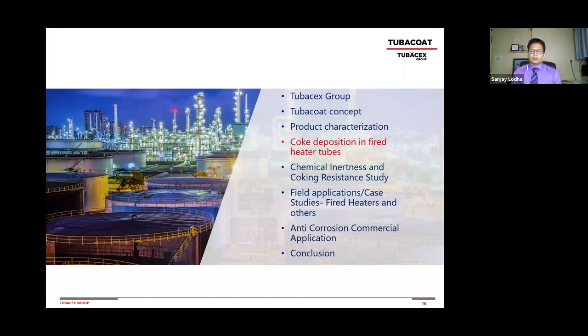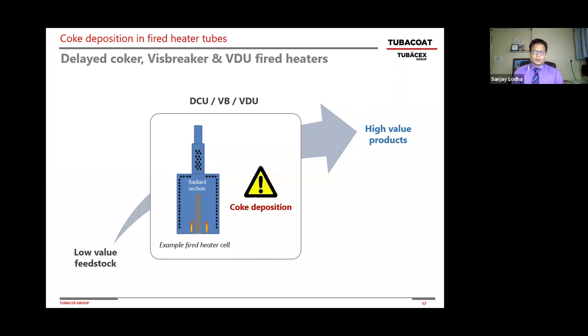Now I'm going to explain the coke deposition in fire heater tubes. Next slide. I think most of your audience work in a refinery, whether in a visbreaker, a delayed coker, a crude unit or a vacuum unit. We know we have these high conversion process units that process low value, heavy feedstocks, whether gas oil, vacuum residue or atmospheric bottoms, and you try to go through a conversion unit to make high value distillates or clean fuels. I'm showing a picture here of a delayed coker. Besides the distillates, you also make coke. In the process, you're thermally cracking the feedstock and creating coke that deposits in the radiant section of the furnace, and that is a problem.